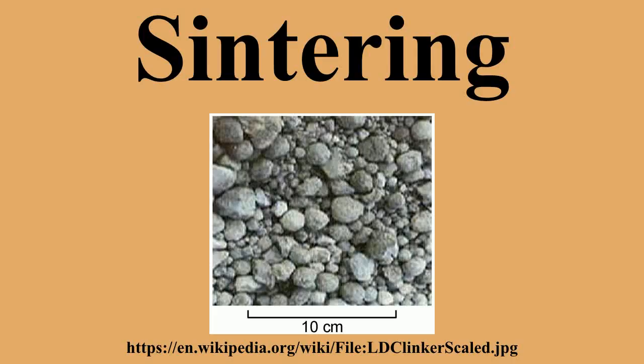Small catalyst particles and a high reaction temperature are in general both factors that increase the reactivity of a catalyst. However, these factors are also the circumstances under which sintering is occurring. Specific materials may also increase the rate of sintering. On the other hand, by alloying catalysts with other materials, sintering can be reduced. Especially rare earth metals have been shown to reduce sintering of metal catalysts when alloyed.